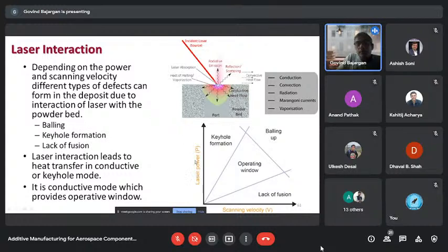So this is laser power and scanning speed. If my power is lower and scanning speed is high, we will end up in lack of fusion. If power is very high and speed is lower, a lot of energy we are pumping in, so it will lead to a keyhole formation. This is the operating window where we want to confine ourselves. And if my power is high and speed also is high, we can end up in the balling effect.